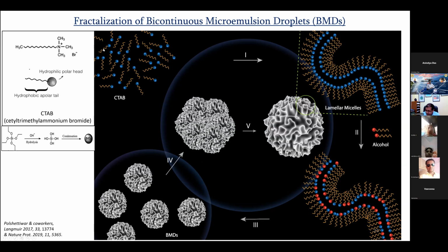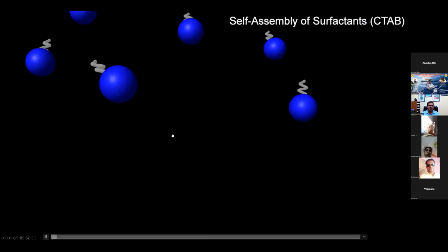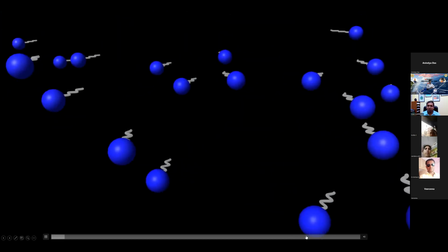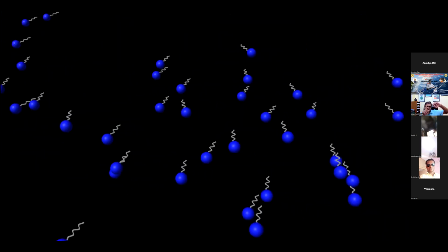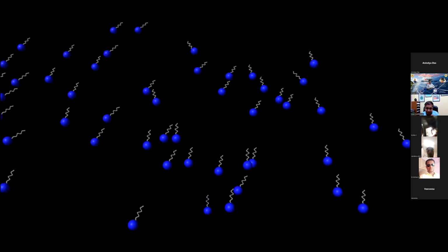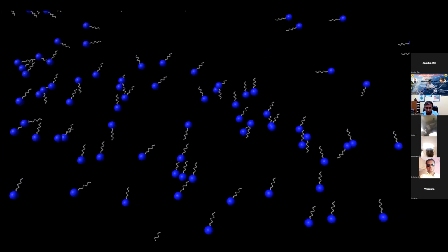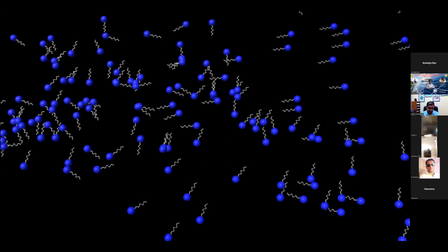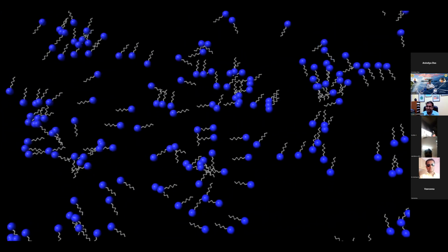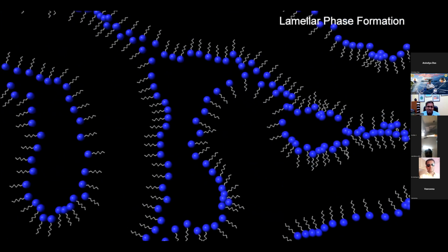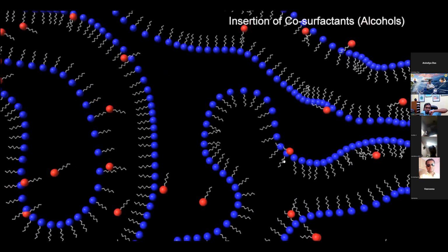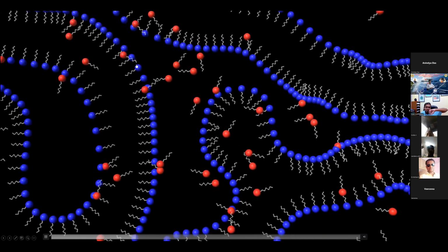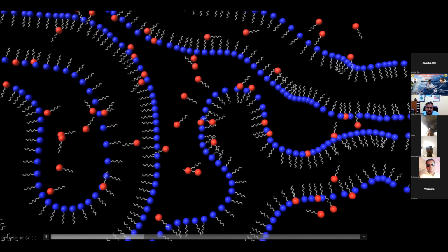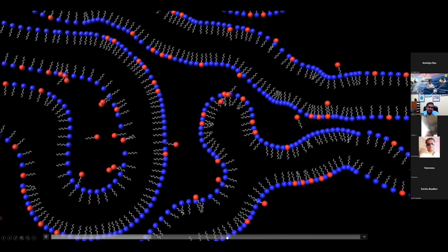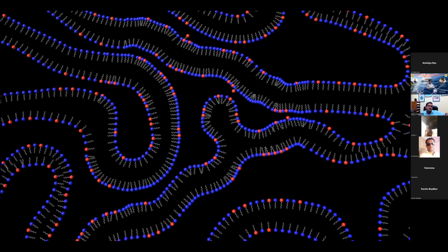So I will show you the animation. When we add these CTAB molecules, the polar head is the quaternary nitrogen, and the zigzag line is the long hydrocarbon chain. We add them into solvent, a mixture of water and xylene, 50-50%, polar and non-polar. The concentration of these CTAB molecules is such that they form these lamellar phases. Now there could be repulsion between the quaternary nitrogens, so we added one more molecule, a co-surfactant, which is pentanol or hexanol. They reduce the repulsion and stabilize the interfaces.